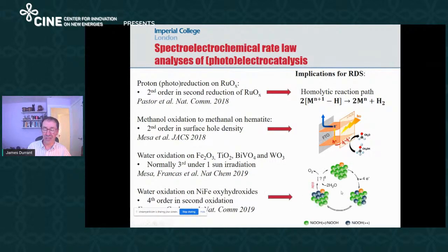As I've just discussed, we observe that water oxidation on nickel iron oxyhydroxides is typically 4th order in terms of hole density. It turns out some of these orders are pH dependent. I won't have time to go into it today, but it looks like reaction mechanisms depend upon the details of the electrolyte environment and indeed how you make your material.